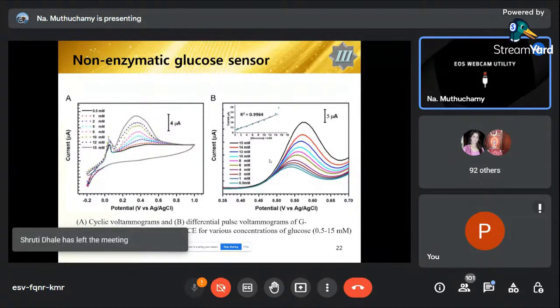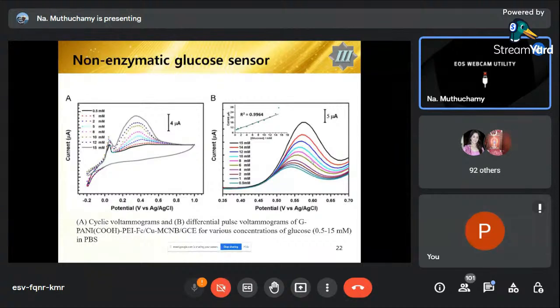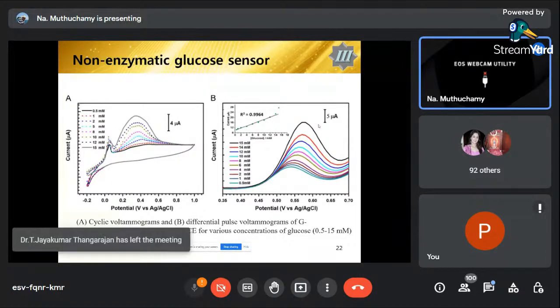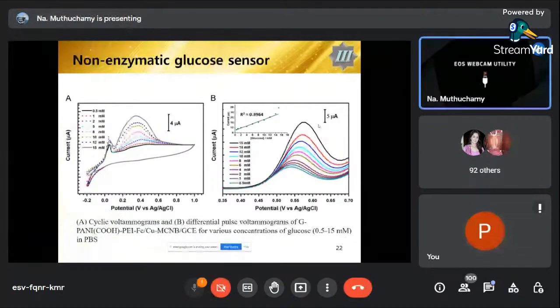In this work we can utilize it for industrial sensors, but in a real human serum sensor we cannot, because when we increase the concentration, the potential is shifting towards the positive side. When we go for a real glucometer, we cannot fix the potential. So for that reason, this material we used for glucose monitoring in alcohol factories. The linear range is from 0.5 to 15 millimolar.